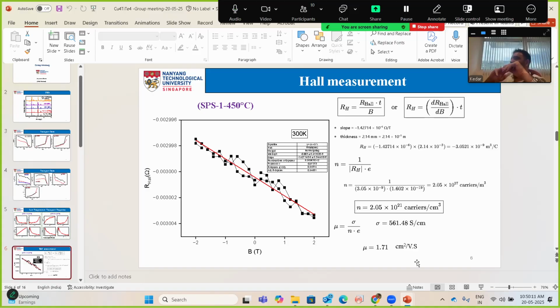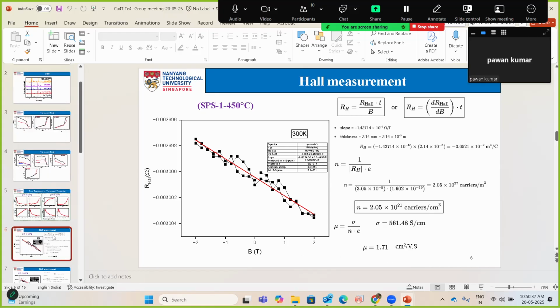So I think the rule of thumb, Jayanta, is that every order of magnitude drop in the carrier concentration will, generally speaking, increase the mobility by one order of magnitude. You look at the number now, 1.7. If you somehow drop your doping level to 10 to the power 19, you will end up getting a mobility of 170. That's fantastic. Maybe get the effective mass and try some modeling, then you have some idea what range of mobility to expect. Just plot some Pisarenko plot and all those things.